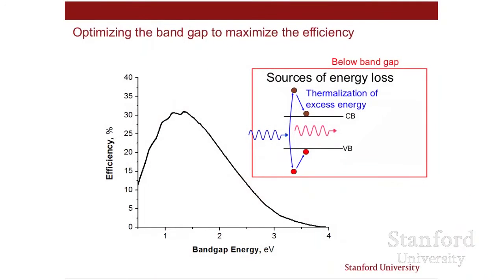And the band gap is really important because if we have a large band gap, then most of the photons in the solar spectrum don't have enough energy to get the electron up into the conduction band, and so we can't absorb those photons. On the other hand, if we pick a small band gap, then the photons excite the carriers high up into the band, and then they fall to the bottom of the band in a process we call thermalization, and we lose all that energy. And so with a low band gap, we get a low voltage.